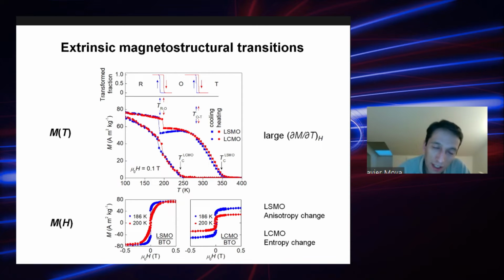And these actually give you large values of the temperature derivative of magnetization, which is a signature of large caloric effects, large magnetocaloric effects. So this is something that points to you that you can use these materials for that application. But then if you look into a bit more detail, if you do magnetization as a function of magnetic field measurements just before and after the transition, you can see that the two materials actually behave quite differently.